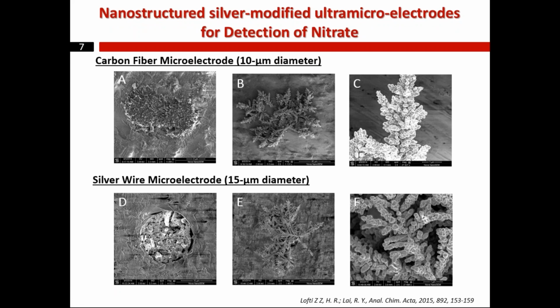Then we collected SEM images of the electrode. So what you see here is the cross-section image that we got with SEM. Pictures A and D are showing the bare carbon fiber microelectrode and bare silver wire microelectrode. And as you can see, the dimension for the carbon fiber microelectrode was around 10 micrometers, and for the silver wire it was around 15 micrometers.